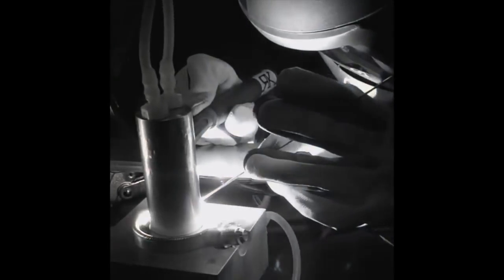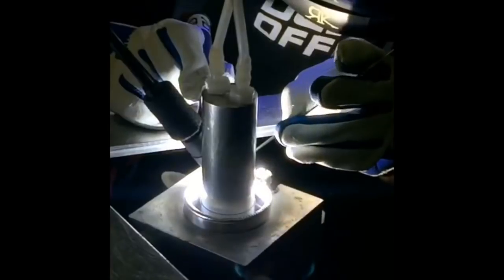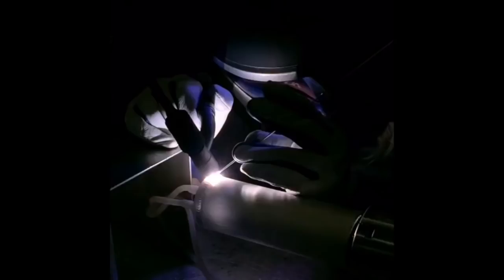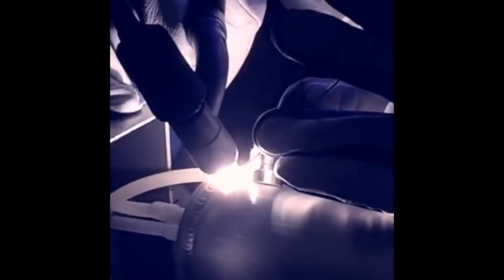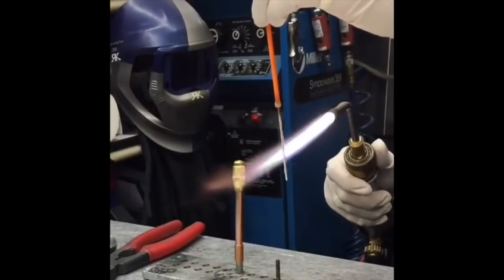But you say it eliminates preheating in a lot of cases. And for me, that's kind of what using a helium mix does, where me and Roy both just mix it to what feels right. We use a Y, mixing helium in with the argon, and just barely crack the helium till we get the puddle and arc that we want. They have mixers out there, I know, and I also have a pre-mixed bottle of like 20% helium, but it helps again with preheat. Like it puddles immediately on most stuff unless it's super thick. The more helium, the quicker it puddles on thick stuff.